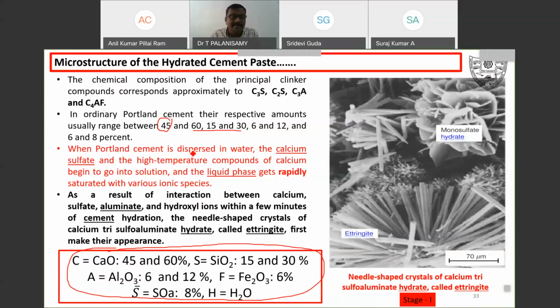Now, when Portland cement is dispersed in water, what will happen? The calcium sulfate and the high temperature components of calcium begin to go into solution, and the liquid phase gets rapidly saturated with various ionic species. As a result of interaction between calcium sulfate, aluminate, and hydroxyl ions, within a few minutes of cement hydration, needle-shaped crystals of calcium trisulfoaluminate hydrate are formed. I already told you that the needle-shaped structure that forms is called ettringite.